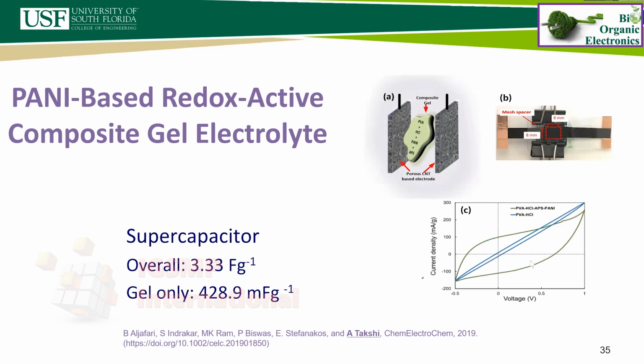So more importantly, we put it between 2 porous electrodes, and we got a very high capacitance. That was a contribution of a little bit of the gel showing some capacitive effect, and also the double layer charges at the electrolyte interfaces. And when we just put this gel on the titanium oxide electrode and the carbon electrode, we could get the hybrid device with up to 138 millivolt open circuit voltage when the light was shined on it.